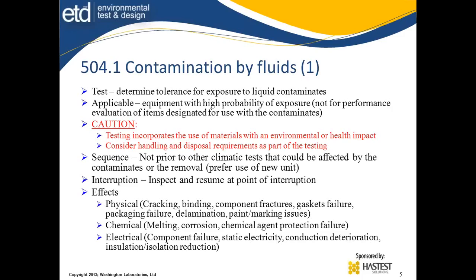Sometimes static electricity can be developed because of the removal of the ions on the atoms. Conduction deterioration. This is especially prone to EMC gaskets and fingers and things like that, where the fluid creeps in and causes an insulating layer so you don't make the connection you should. Or it produces insulation and isolation reduction, where circuit board traces no longer have the separation they need, and arcing tends to happen between circuits. So you watch for these kinds of events, and that's part of the inspection.